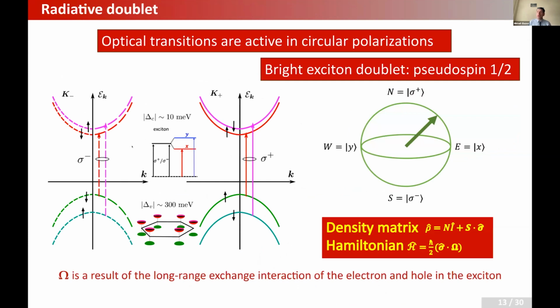So since we are dealing with optically active excitons and we are dealing with two states, sigma plus or sigma minus polarized, in the absence of any perturbations, they should be degenerate. So we deal with a standard two-level system. So we can describe the bright exciton radiative doublet as a pseudo-spin 1/2, just like the electron spin. The meaning of the spin components will be, however, different. So Sz would give you the degree of circular polarization, but in-plane pseudo-spin components will give you the degree of linear polarization. It is very much similar to the Stokes parameters and to the polarization density matrix of light.